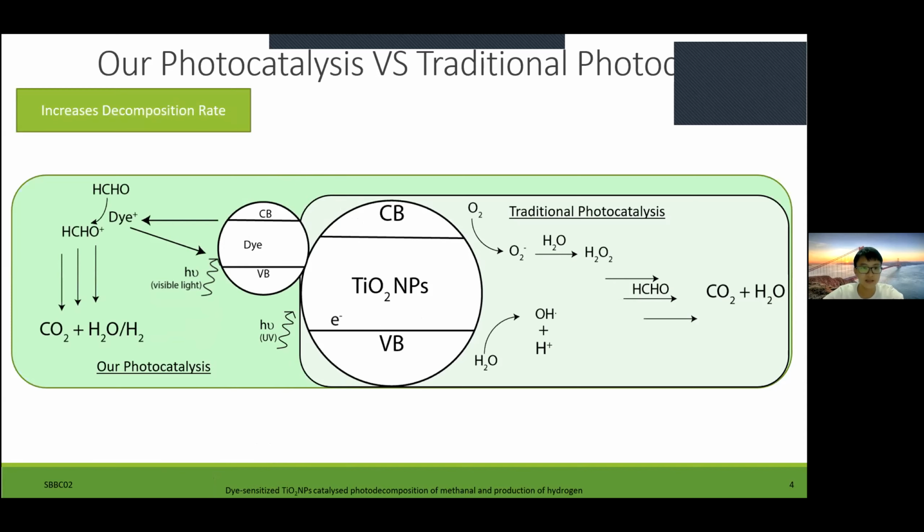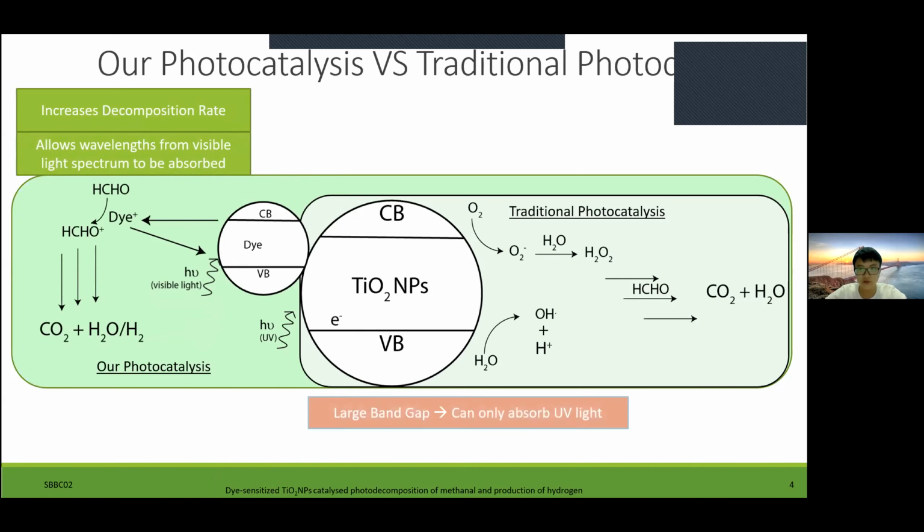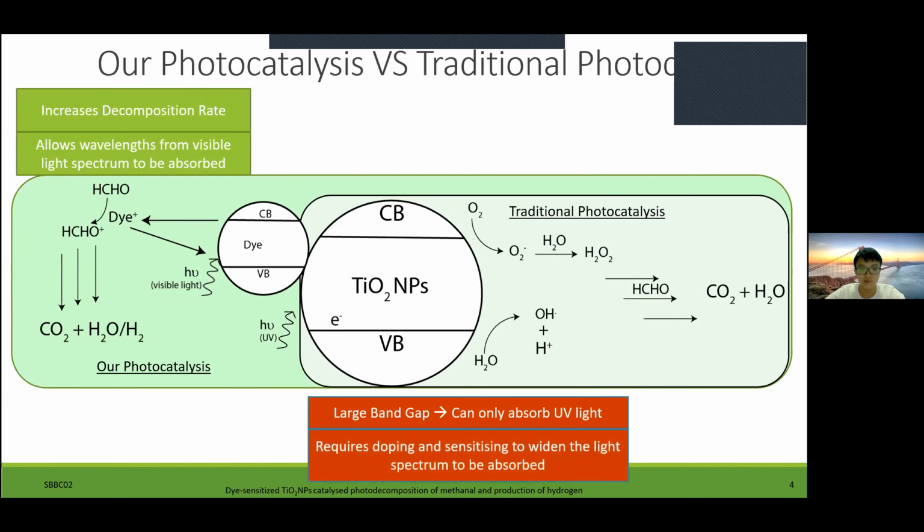So our photocatalysis method increases the decomposition rate and allows the wavelengths from visible light spectrum to be absorbed, compared with the traditional one, where titanium dioxide nanoparticles have a large band gap and can only absorb UV light, and hence requires doping and sensitizing in order to widen the light spectrum to be absorbed.